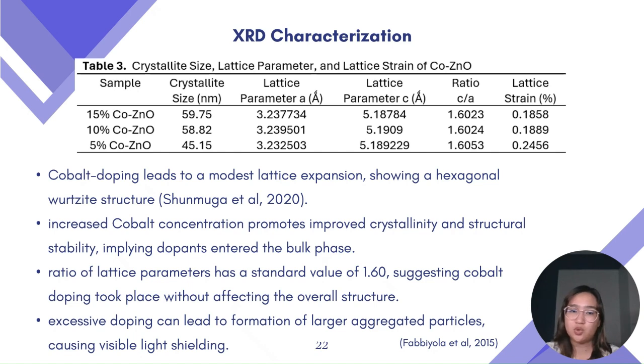Under the synthesis condition and doping range, cobalt seems to promote grain growth due to the increasing crystallite size with higher doping, suggesting that cobalt incorporation leads to a modest lattice expansion. This is likely due to a local strain relaxation or possible dopant clustering with higher doping. The trend of increasing crystallite size, along with decreasing strain as cobalt increases, is consistent with dopant-induced grain growth and reduced strain. Moreover, the observed reduction in lattice strain with higher doping levels supports the idea that increased cobalt concentration promotes improved crystallinity and structural stability, implying that the dopants entered the bulk lattice.